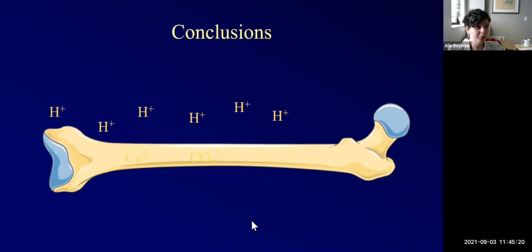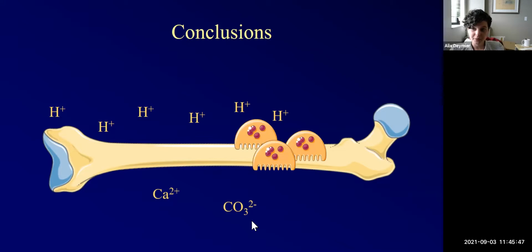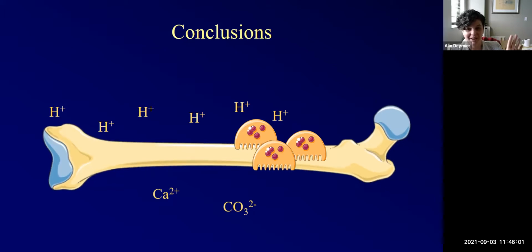So overall, what we found by looking at all 3 of those levels is that when acid interacts with bone, we have release of calcium and carbonate. The carbonate level within the bone goes down. Your mineral crystals get stiffer. But if you have cells, you're also getting less mineral on the interior. We know that acidosis does promote the formation of cells. However, that formation of cells seems to be temporary. We don't see a lot of long-term changes to that. That behavior of the cells doesn't appear to be responsible for the changes in mechanics.